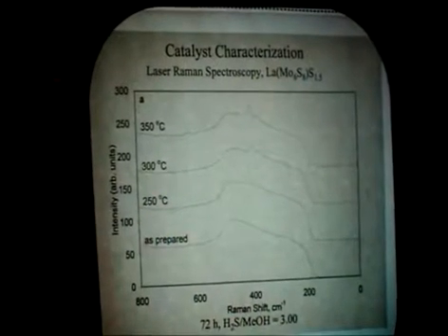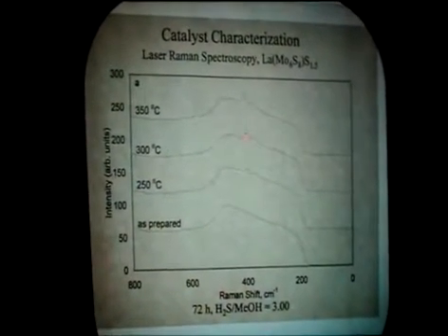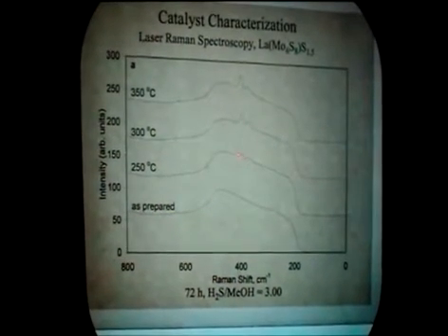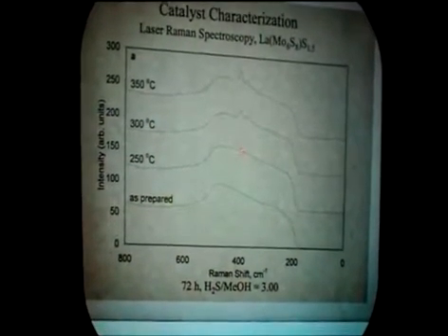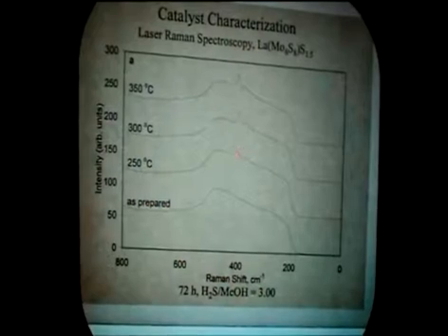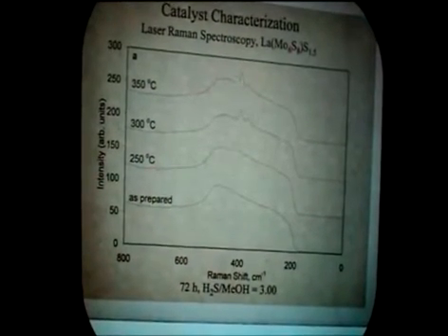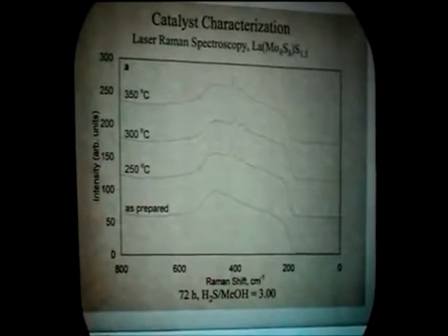Now, raising the temperature with the lanthanum material, we also start to be able to detect MoS2. Even if you're creative, you can see a peak here at 250 degrees C for MoS2. But then again, by 350, it's pretty clear that by laser Raman we can detect MoS2, even on the lanthanum material.